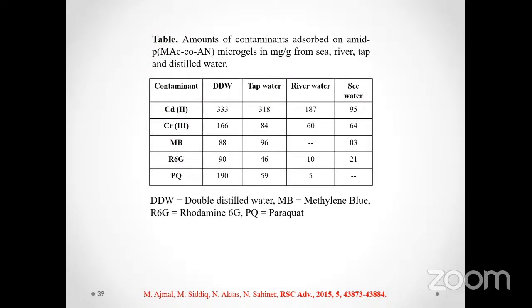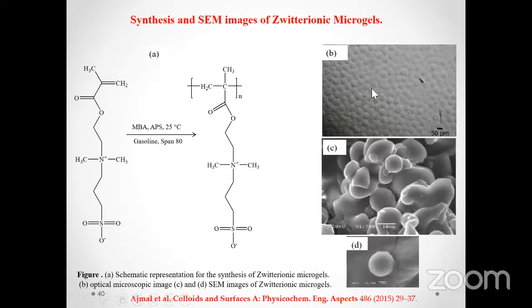So this system was also used for real applications in double distilled water, in tap water, in river water, and even in sea water. The contaminations were dissolved in the sea water, in the river water and in the tap water, and it was observed that the system was effective for all these mediums, although the adsorption capacity was decreased in the case of river and sea waters. But this can be due to the presence of different metallic salts in the sea and river water, which can also be adsorbed in the hydrogel network, and they can occupy the adsorption active sites.